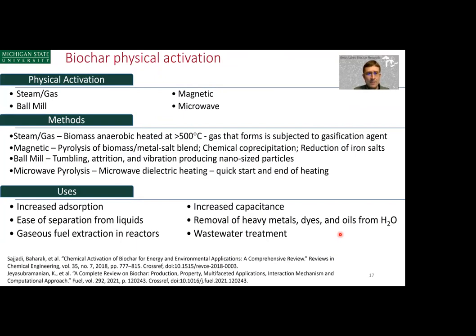A number of folks have wondered about different activation techniques. Classically, biochar is activated most often by steam, where the steam is usually high pressure, high temperature steam. What this serves to do typically is to increase the surface area of these biochars to make activated biochars or activated carbon. Having activated carbon is important because it'll increase the adsorption and removal of such contaminants as heavy metals or dyes or oils from water streams or from air streams.